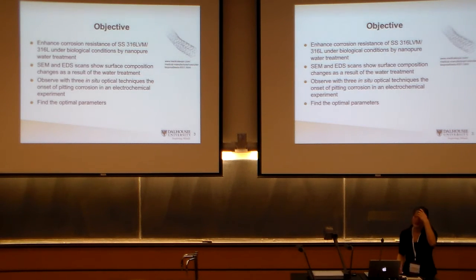So our goal for this research was to make stainless steel less corrosive in biological conditions for medical applications such as cardiovascular stents or other applications. We've done this by submerging our samples in nanopure water at 90 degrees Celsius. This changes the composition of the surface enough to prevent the onset of pitting corrosion at low potentials. We've seen these changes in composition on the surface using scanning electron microscopy and energy dispersive X-ray spectroscopy scans before and after our water treatment.